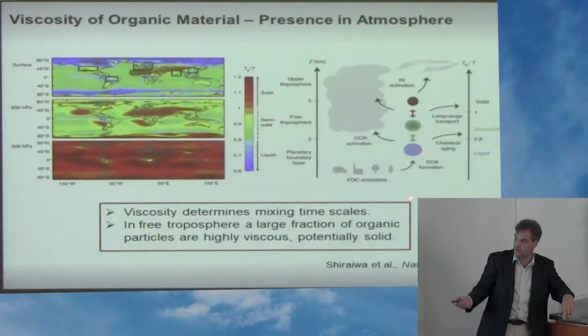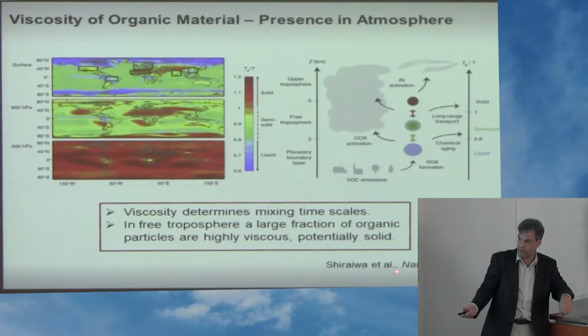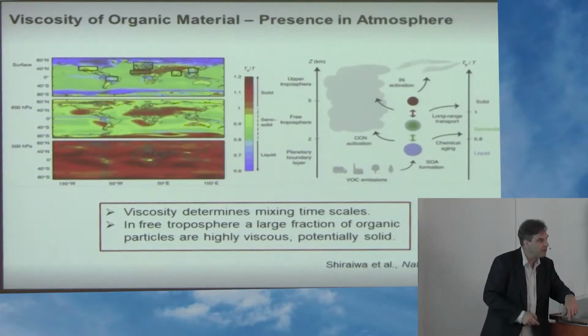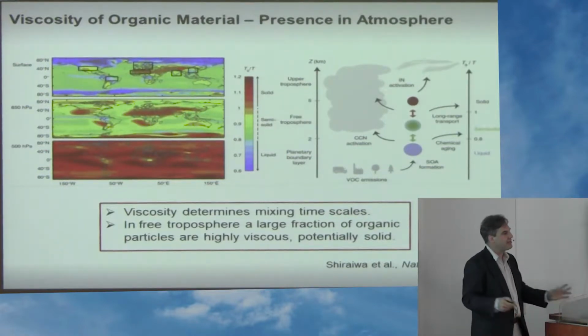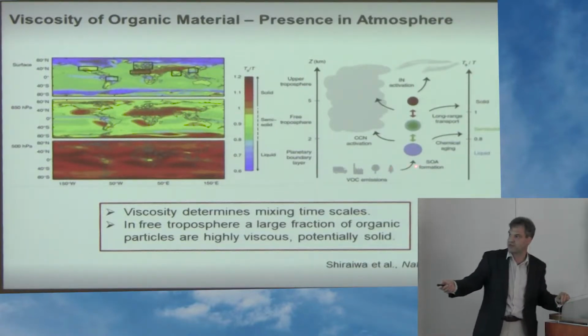And here's a very beautiful paper by Shiraiwa and co-workers, and they try to estimate the phase of secondary organic aerosol as a function of height, and red means they're solid. Close to the surface, from the knowledge of the chemical composition of the particles, there are regions where they are solid, in particular dry regions, but just a kilometer or two up, you get a vast amount of solid glassy particles, and at 500 hectopascal, 5 kilometers in height, all SOA is solid, glassy.